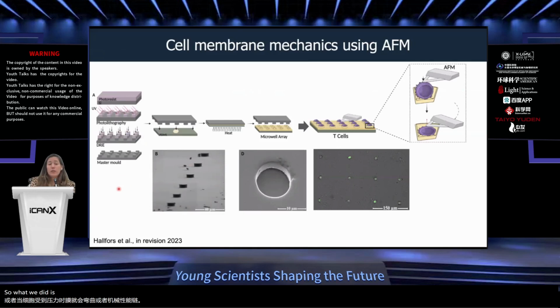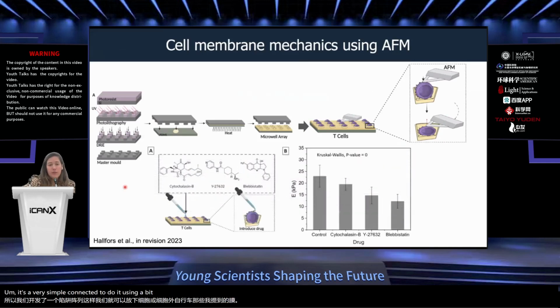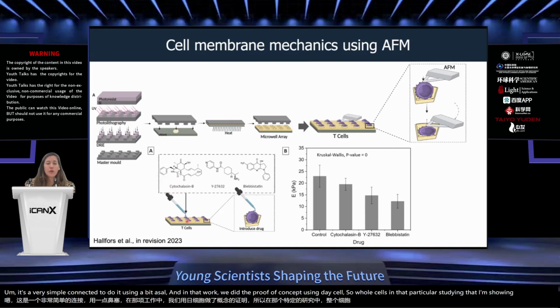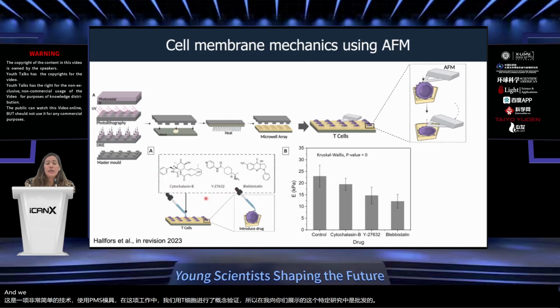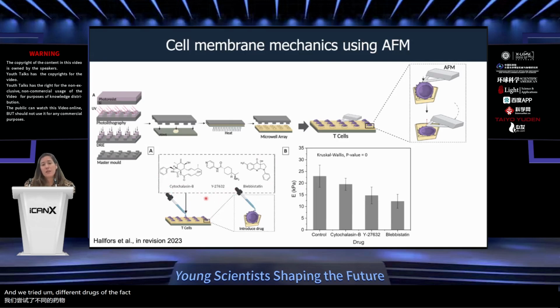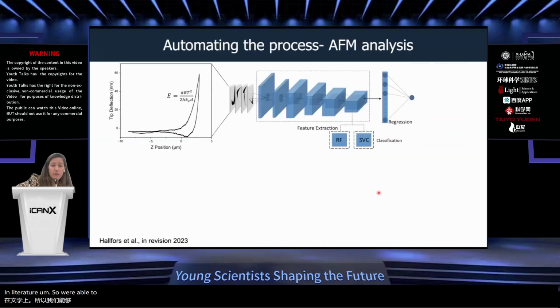So what we did is we developed a trap array. So we can trap cells or extracellular vesicles, those membranes that I mentioned. It's a very simple technique to do it using a PDMS mold. And in that work, we did the proof of concept using T cells, so whole cells in that particular study that I'm showing you here. And we tried different drugs that affect the cytoskeleton. So we would expect to decrease the Young's modulus, as shown in literature. So we're able to see differences experimentally.